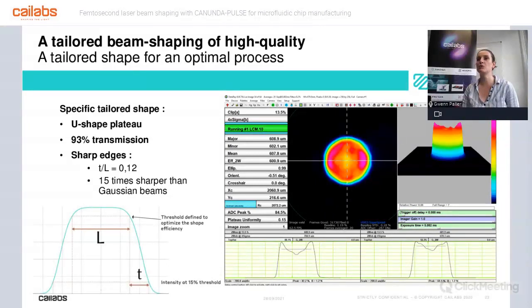It was the first time that we do some processing using this shape. We didn't really have a name for it, so now we will call it the U shape, because you see it's just like a U. With more energy in the ring at the output of the shape and less energy in the center. So this is really interesting, because when you scan using this shape, you will have a constant energy hitting the material, and this will be described later on by Mark.